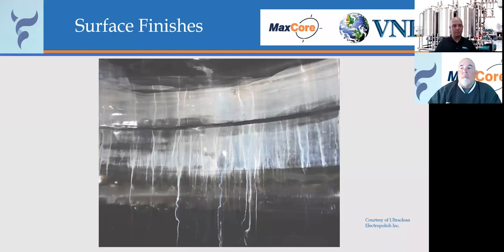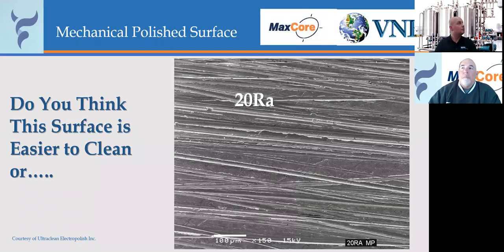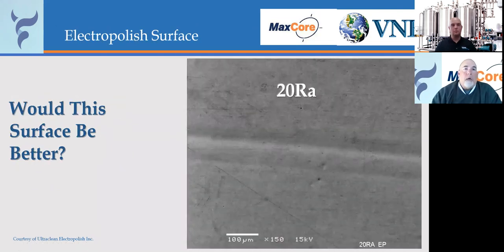So when we're talking about material surface finishes, this is a 20 RA mechanical polish surface. If you look at it, you can see the cuts and grooves from the sandpaper, and some areas of the material that have folded over itself. This next slide shows a 20 RA electropolished surface. All of that damaged area has been removed and you just have a nice, smooth, featureless surface.